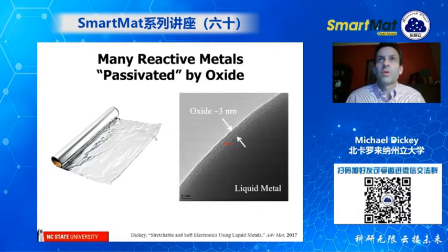Now, let me tell you a little bit more about this oxide layer. Pretty much all metals other than, say, gold and platinum will react with air and form what's called a passivating oxide, which just means it forms an oxide and it stops. And so this is a picture of aluminum foil, and it reacts with air and forms an oxide. In the case of the liquid metal, it also forms an oxide layer, and that oxide layer is about 3 nanometers thick. It's very, very thin, but it has a profound effect on the way this stuff behaves.